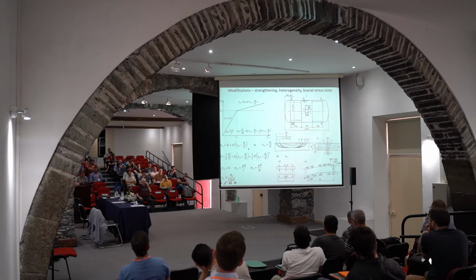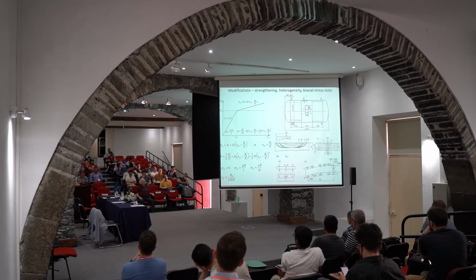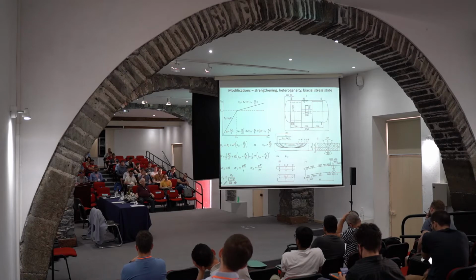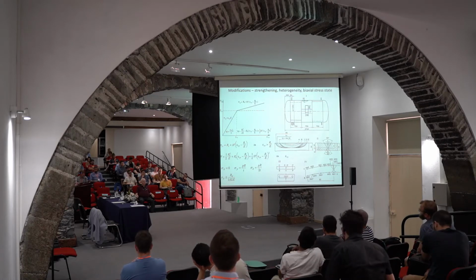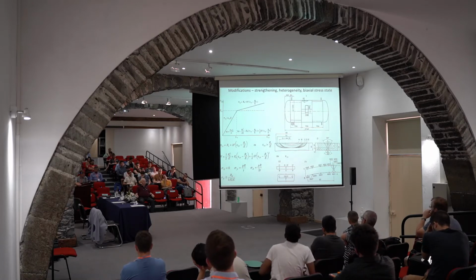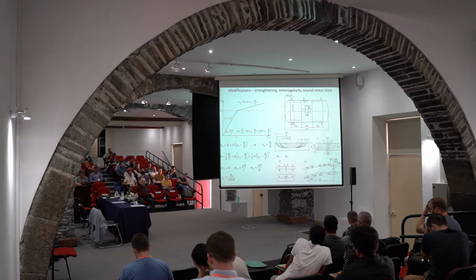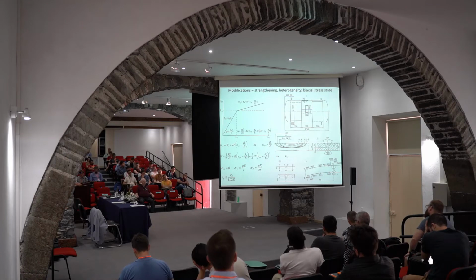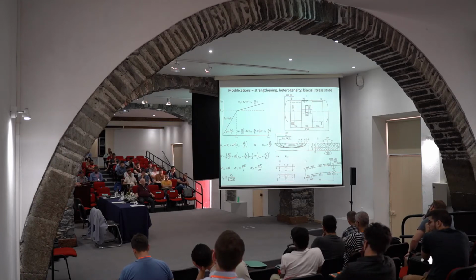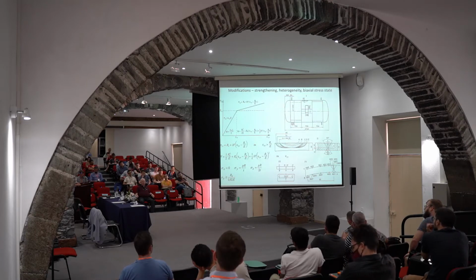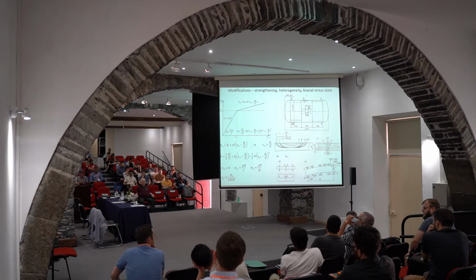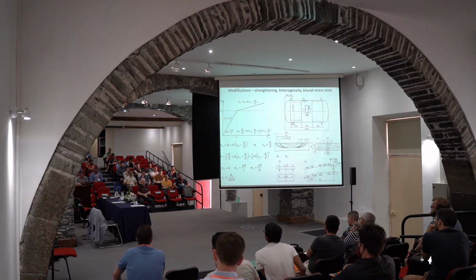And what we also did is to evaluate the effect of biaxial stress state, because it's not the same as uniaxial, but it turned out that the difference is just 2%. You can see it at the bottom of this left column, that actually this criteria for yield strain is just 2% lower than in uniaxial stress state. But this biaxial stress state is for cylindrical shape, and in the case of spherical shape, and spherical pressure vessels are a bit more critical, the difference is significant. So once again, good knowing of what is behind the story enables us either to neglect something or to be sure that we have to take it into account.